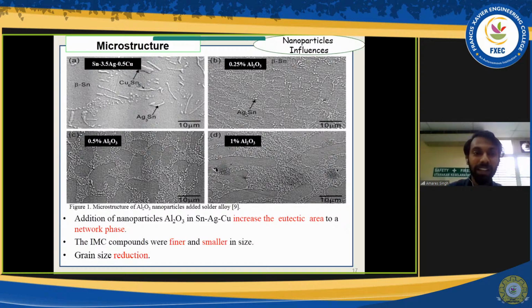You can see that in the pictures of A, B, C and D, there is a pattern. So let's take it as an island. You can see that the island grows when the nanoparticles are added. These islands are known as eutectic area. Eutectic area is a point where you have many compounds. For example, you have argentum and tin and the nanoparticles at the eutectic area. The eutectic area will have more than one compound and also combinations of compounds, intermetallic compounds. These intermetallic compounds are important to actually resist deformation.